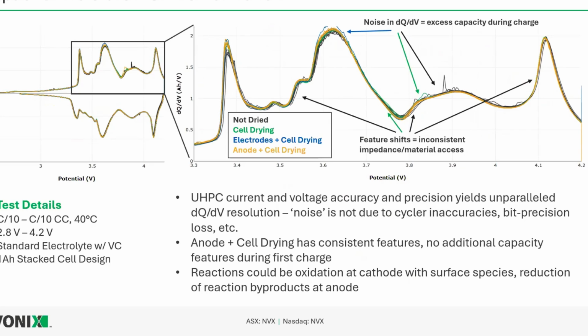Another really good benefit of using UHPC, as I've mentioned before, is DQDV. So you can see here, when we blow up this DQDV, we're seeing some normal noise that you may be used to seeing when you look at DQDV. But with UHPC, there really is no inherent noise like this. We don't smooth any of our UHPC data. A good cell should have almost no noise within this curve. So anything that you see here is actually real. And we can see as we move through these groups, the consistency within all of these traces increases as we get to this final group.